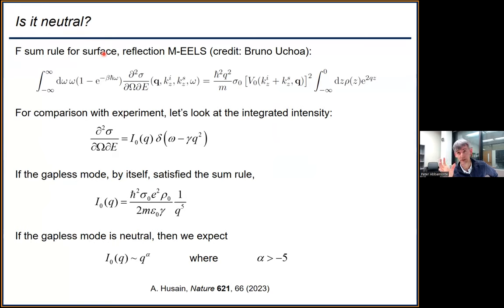But the thing that made this complicated is the fact that this is a surface measurement, and you measure a surface susceptibility. It's not the same as the one that you compute in RPA. So you have to compare to the sum rule for the susceptibility that you're measuring. And if you go into the literature, it turns out no one has ever derived a sum rule for the surface EELS susceptibility. It's never been done. So I would like to credit Bruno Uchoa from Oklahoma State for actually working this out for us. He went through all the commutators and computed the F sum rule for the surface EELS response. It's in the appendix of this paper.